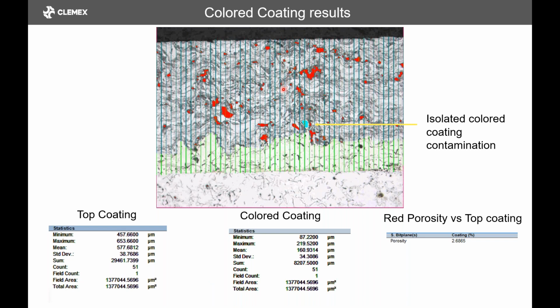And here's an example, the result at the end. So we can see the greenish line here, the darker green, and then it's following the curve of the coating, and we have our green coating, that is our bond coat, and we have the results. So we have a minimum, maximum, standard deviation for the top coating, the bottom coating, and also we have, I'm not sure if you're seeing this or not, red porosity versus top coating. So we have detected the whole ceramic coating, and then we can measure the porosity area percent versus